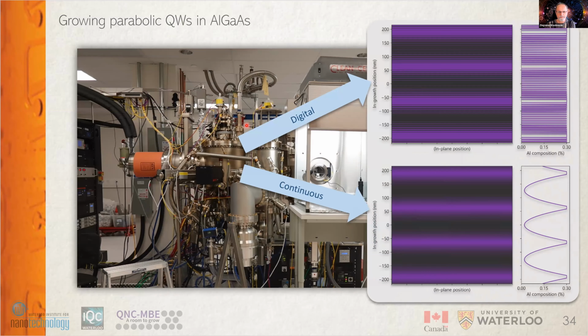Now, the parabolic quantum wells is a big challenge. It has been a big challenge till we started to work on that. They have been pursued typically with so-called digital grading, where you keep opening and closing shutters, putting a little bit of aluminum, a little bit of gallium. That creates a lot of interfaces, not very good scattering, not very accurate. So we needed a continuous smooth gradation parabolic quantum wells. And this is again Chris, he came up with the way to do that, which I wouldn't say revolutionized molecular beam epitaxy, but I think this was one of the strongest contributions into the field for the last decade or two.